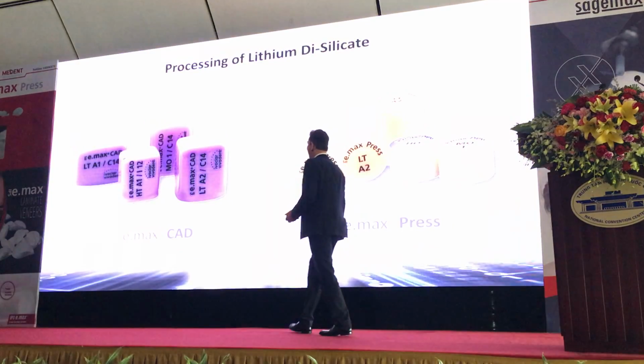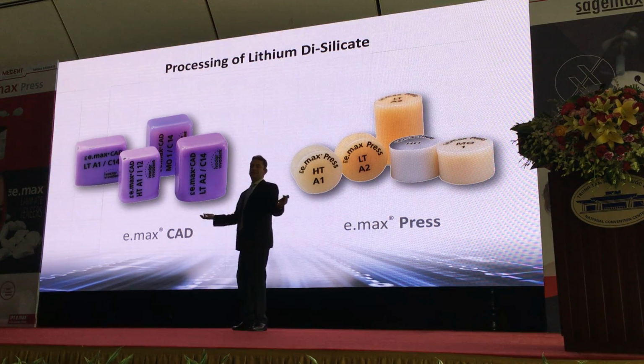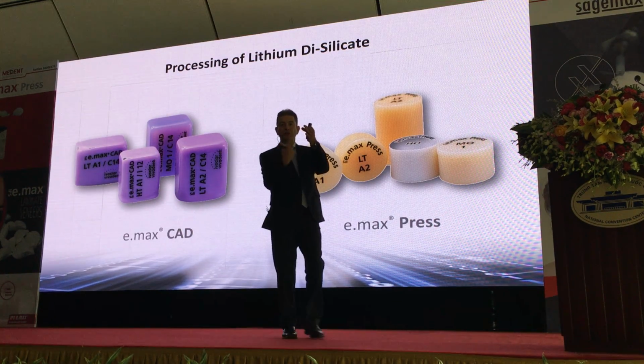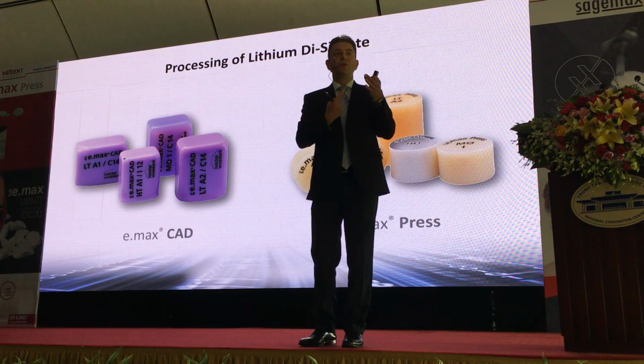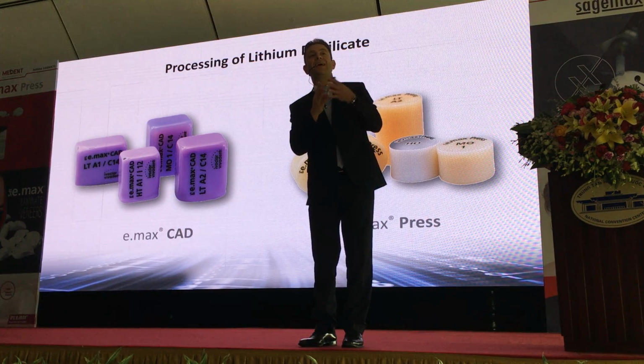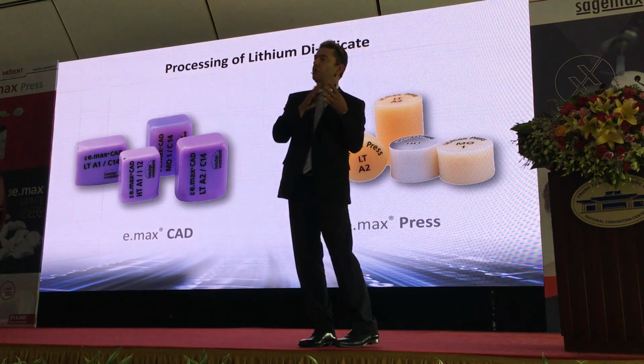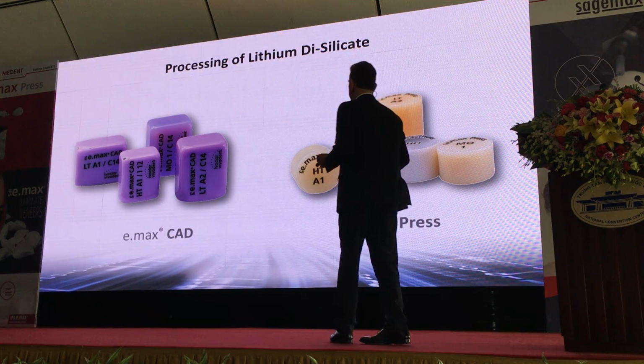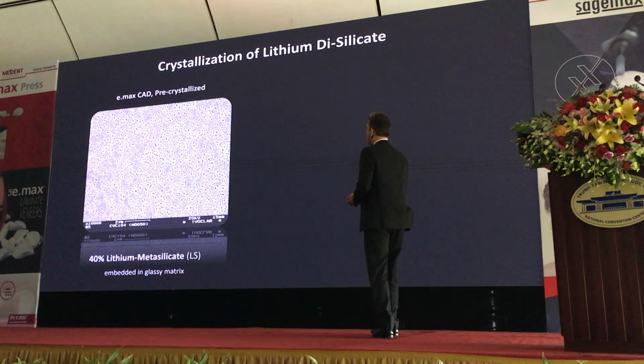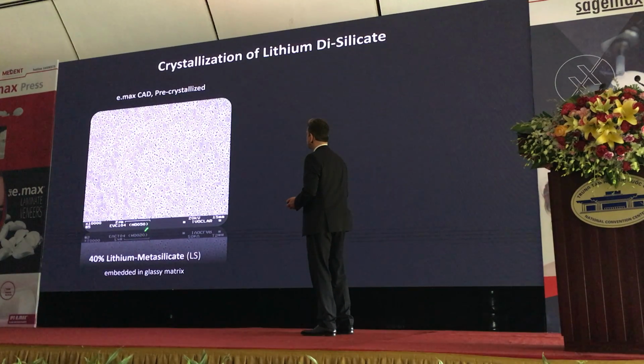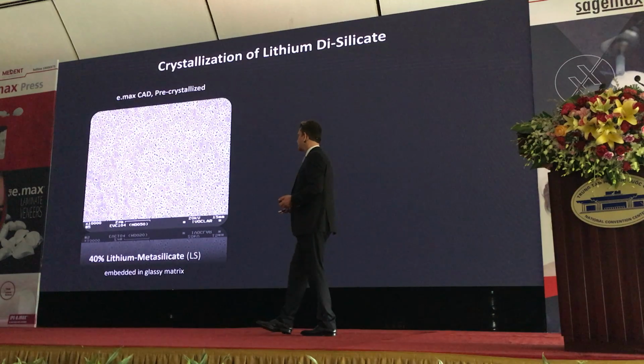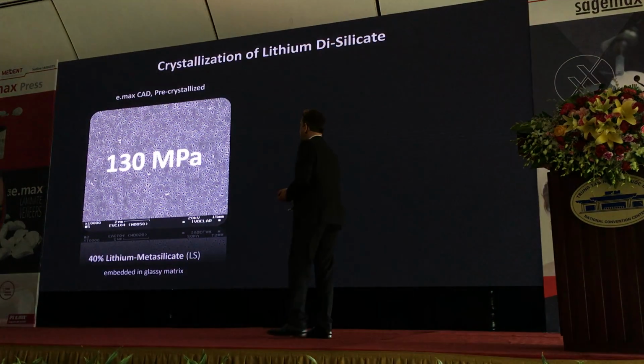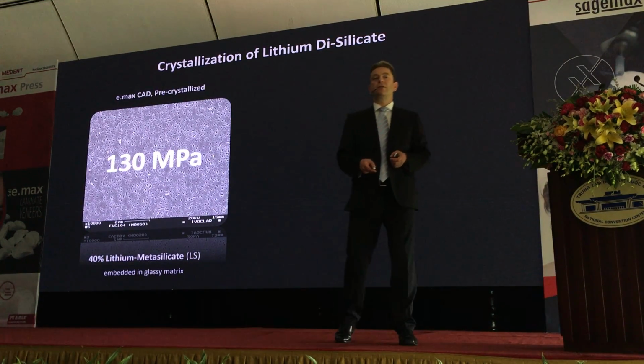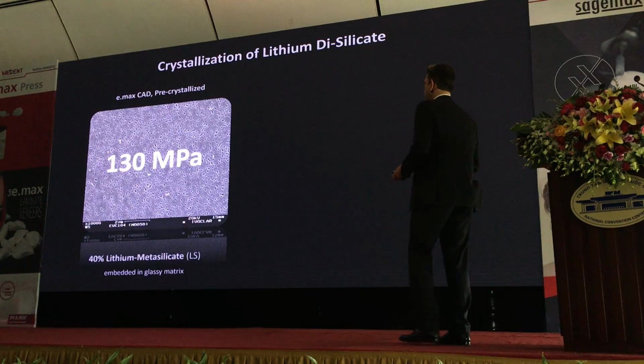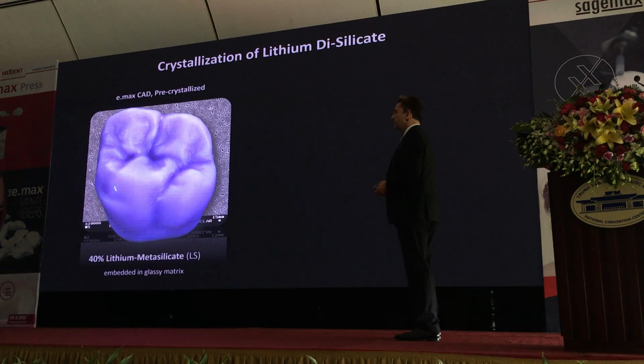But the question is, of course, why do we have a blue block? What's the reason? You know that we need to mill the material. So during milling, the material should not yet have the final strength. It should be a little bit softer so that we can mill it easily and more quickly. So now you can see this is the blue block. This is not yet lithium disilicate, but a precursor called lithium metasilicate crystal. So this is still quite weak. We have only 130 megapascals for easy milling. But then you can see we can mill this crown easily. Within 10 minutes, we can mill it quickly.